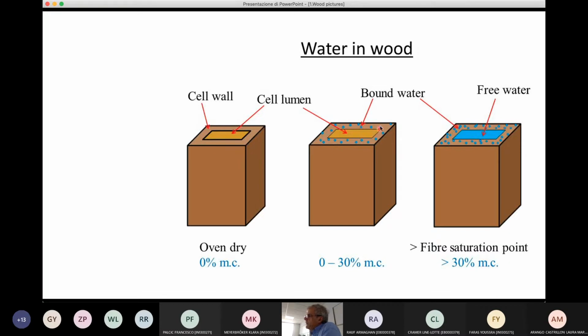So the content of bound water can vary normally from 0% when wood is dried, for example, inside an oven, to a maximum of 30% when wood is placed in a very humid environment. So normally in indoor conditions, the moisture content of wood is around 10%. Normally, it's said that the typical moisture content of a piece of wood ranges from 8 up to 12%.